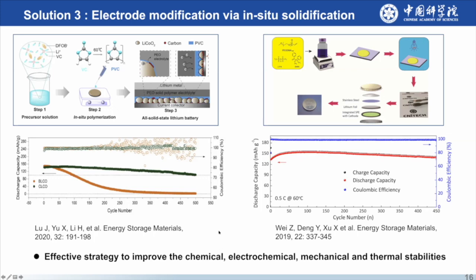With this kind of strategy, you can both improve the chemical and the electrochemical stability, and also you can use the in situ polymerized electrolyte to be compatible with the large volume variation of the cathode and anode during the cycling. This is very important. And also we have demonstrated those kind of in situ formed polymer electrolyte is thermal stable.